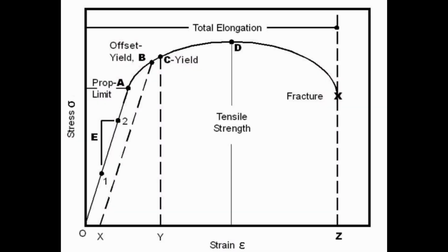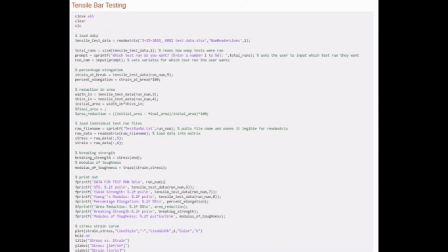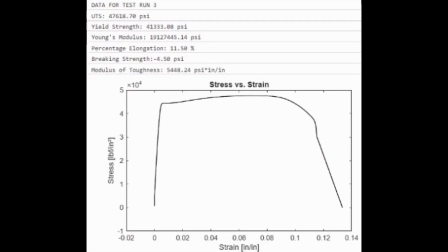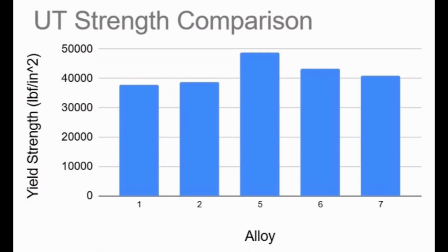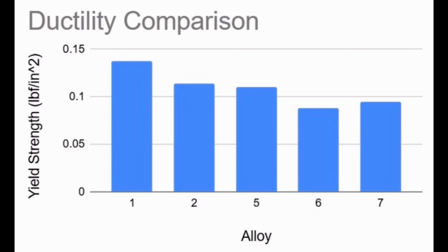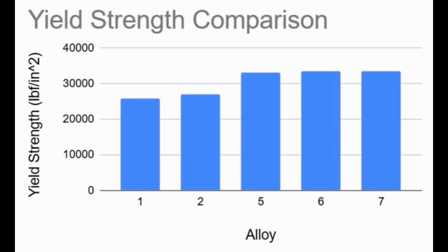The final step in the project was to analyze the data we collected from the tensile testing so that we could determine the strength characteristics of each alloy. Alloy 5 has the highest ultimate tensile strength, while Alloy 1 has the highest ductility. The yield strength of alloys 1 and 2 are comparable, as are the yield strengths of alloys 5, 6, and 7. On average, alloys 5, 6, and 7 have higher yield strengths than alloys 1 and 2.